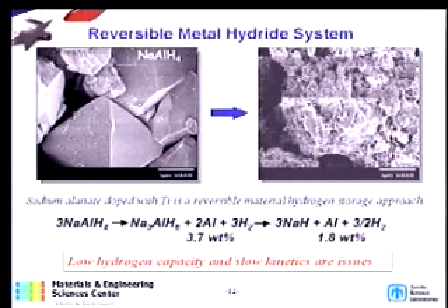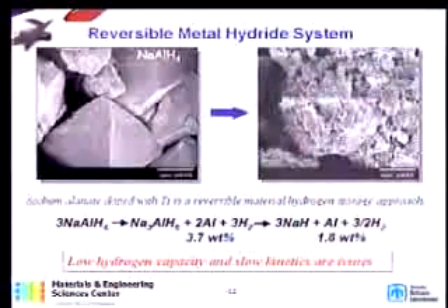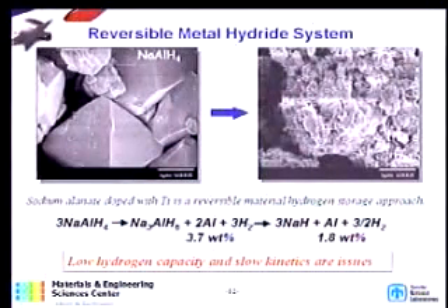And for all the chemists that know, sodium aluminum hydride has really been a reducing agent used for many, many years. It's non-reversible. Until about '96, '97, Dr. Bogdanovic in Germany discovered that use of titanium doping makes it reversible and also with reasonable kinetics. But the problem, as I said, is if you use a two-step you can get up to maybe 5% weight, but the DOE requires at least 6% weight, and also the kinetics right now are still not very fast.